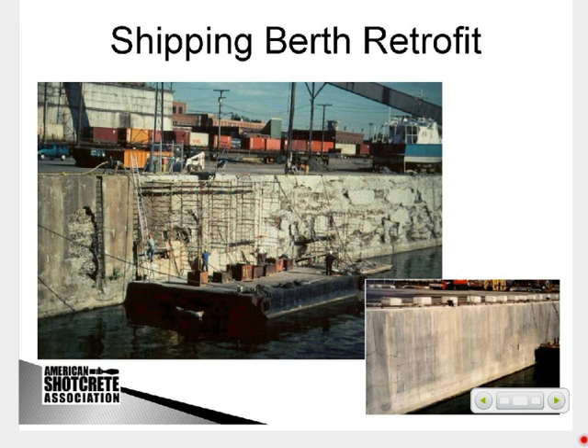And here's a shipping berth, docking facilities. You get a lot of aggressive damage to concrete from the fluctuation in the water. It can be salt content that gets in. The chlorides corrode the embedded reinforcing steel. Maybe the cast-in-place concrete wasn't as strong as it needed to be. So you can see working off a barge, setting up scaffold. As long as you have access to the face where you can prepare the surface and then shoot the shotcrete, you can create a nice smooth surface that's completed. You can see the inset of the completed surface on the lower right-hand side of the slide.